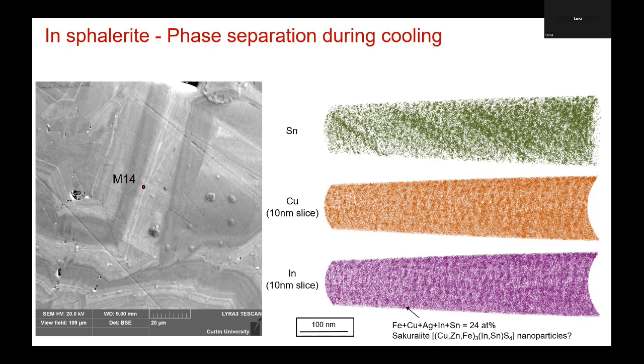And it's so rich that during the cooling, you basically had the spontaneous exsolution of zillions of clusters which are rich in indium, copper, and tin. So here we're probably touching at the phase stability of sphalerite and these trace elements in sphalerite. When it's hot, it can incorporate lots of stuff. When it cools, it sort of rejects them as nanoscale inclusions.